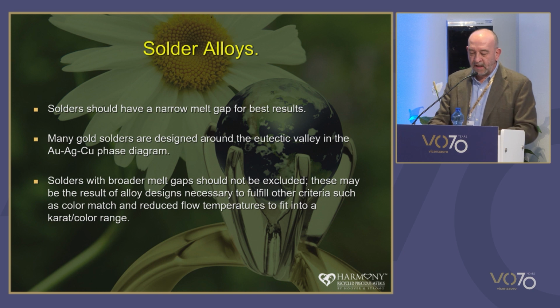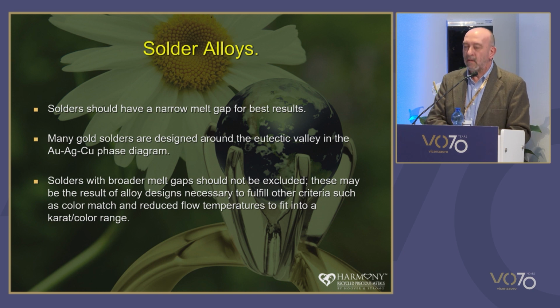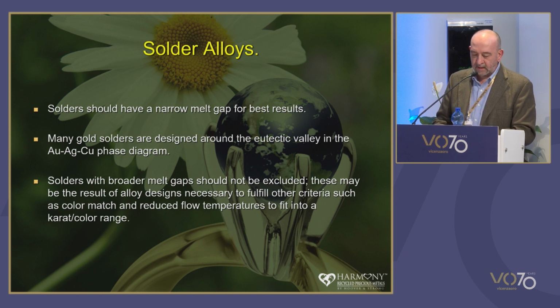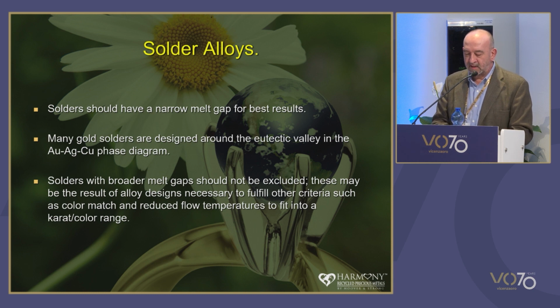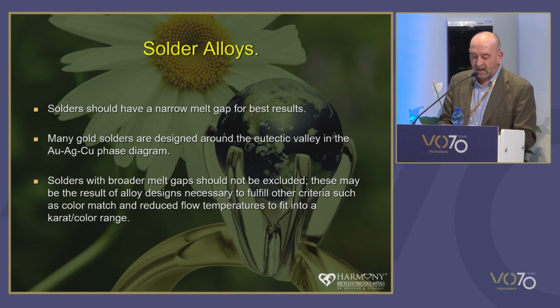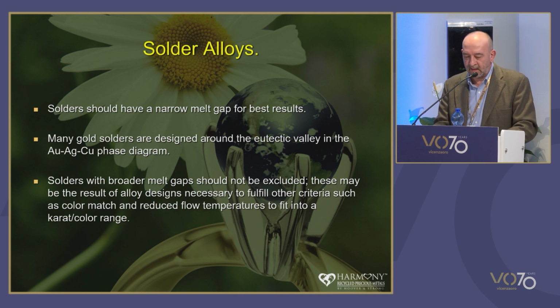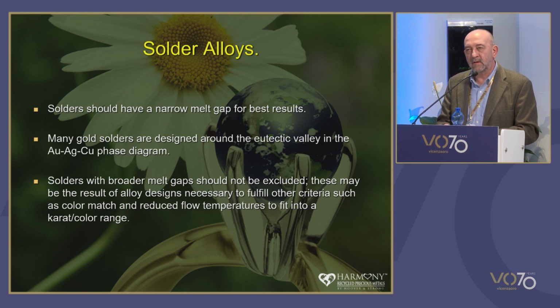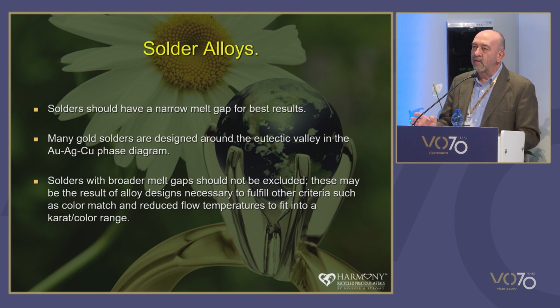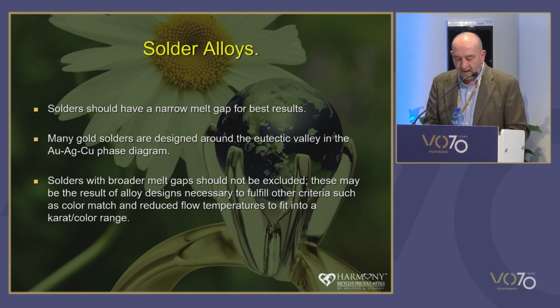So it's generally accepted that solders should have a narrow melt gap for the best results. For gold solders, this often means they are based around the eutectic valley in the gold-silver-copper system, and this not only keeps the melting temperature low, it also keeps the melt gap narrow. Some solders do have quite broad gaps, but this is usually a design around color considerations and where they sit in the soldering process. Color match can also be difficult the further away a solder is from the parent metal in melting range.